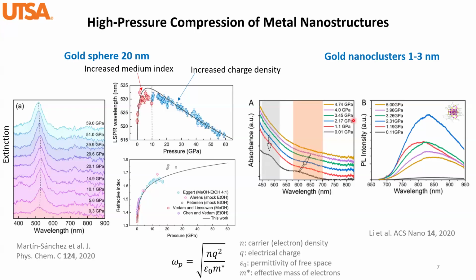Well, in the hydrides, what happens is you create a new set of phonons that are extremely high frequency, so high that they're near resonant with the conduction band. And that really reduces the scattering. But maybe you should try to think about this the other way, which is rather than trying to tune these things, try to figure out theoretically what kind of electron-phonon interaction you would need in these materials to reduce it. I guess what I'm trying to say is, is there a possible way where you can totally minimize the plasmon-phonon scattering? You can't do other things. You can't make it conduct forever or have a mean free path longer than the lifetime. But maybe there's a way of engineering it so that you really reduce the plasmon-phonon scattering, either through composition or pressure or temperature.